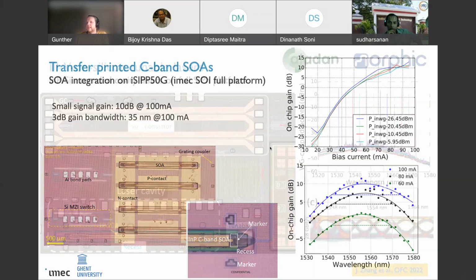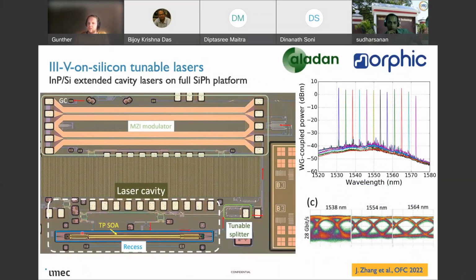Now, using this technology, we also did the first widely tunable lasers on this platform. So you recognize here again the ring resonators that we use to form the laser cavity. And here in this recess, we actually printed the III-V SOA. This picture is taken before the final metallization, such that you can clearly see the III-V coupon. And on this platform, of course, we also have the high-speed modulators as shown here. So this again resulted in a C-band tunable laser, but in this case connected to a high-speed modulator as a proof of principle. This will be presented at OFC later this year.